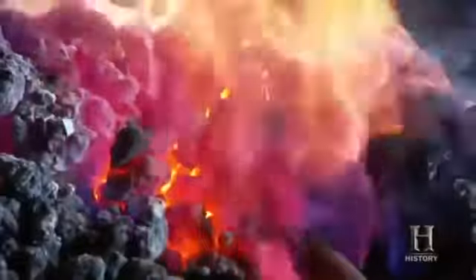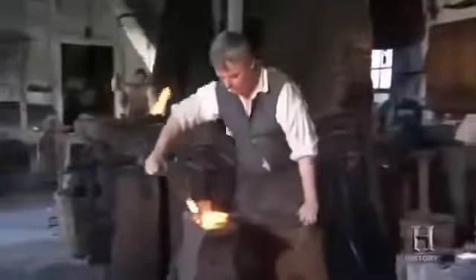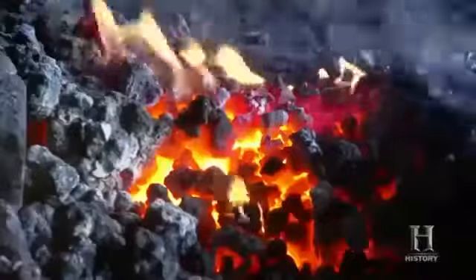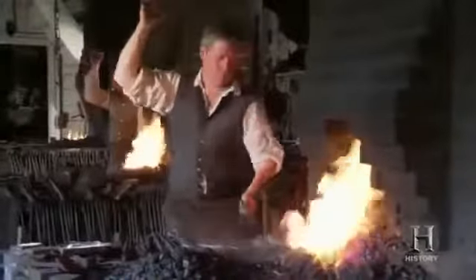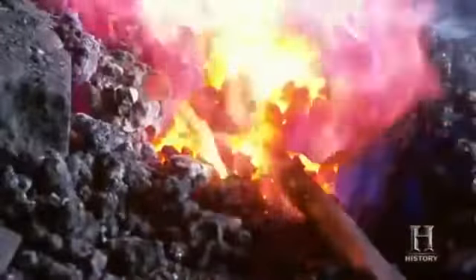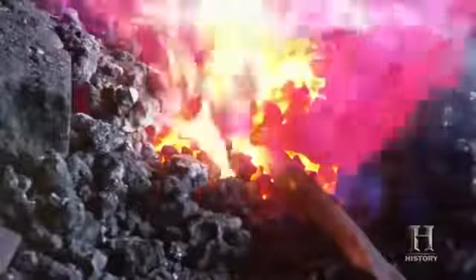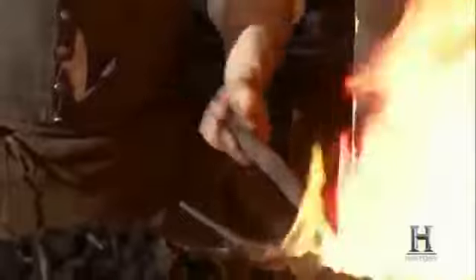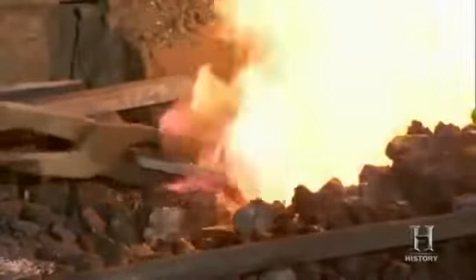But before iron could be shaped, it had to be heated to near its melting temperature of 2,700 degrees Fahrenheit. Such heat was difficult to produce until roughly 1000 BC, when a new technique raised furnace temperatures dramatically. The lever's attached to a bellows. A bellows is an air pump. By blowing air into the fire, we can just about double the temperature. When I put the bar in the fire, it's at a black heat, below 1000 degrees. As it heats up, it'll turn red at about 1000 degrees, then go from red to orange, to yellow, to white hot. White hot is close to the melting temperature, about 2,700 degrees Fahrenheit.